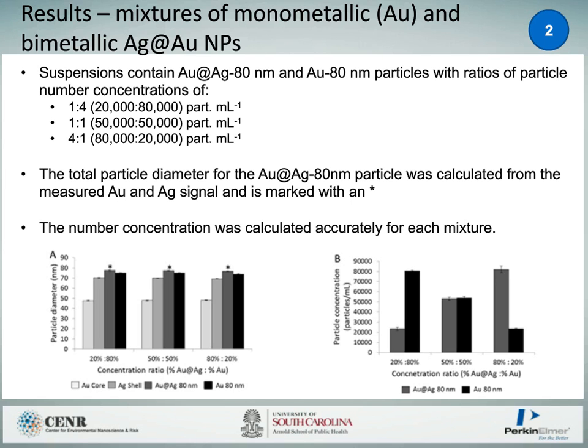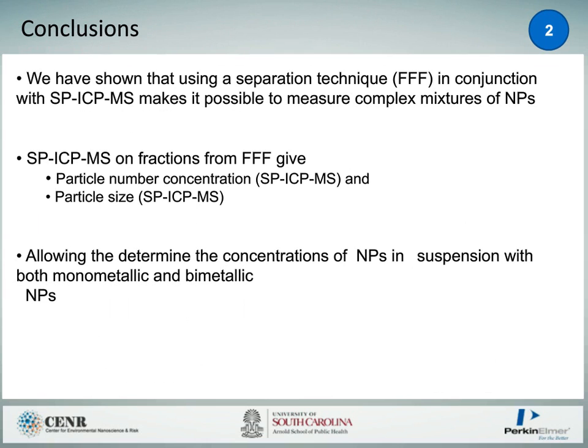So we can actually get the right number of particles and the right size of particles in this case. So I'd like to conclude and say we've shown that using separation techniques like FFF in conjunction with SingleParticle ICP MS, it's possible to measure complex mixtures of nanoparticles. SingleParticle ICP MS on fractions can give you a particle number concentration and a particle size for the particles within that fraction. And we can determine concentrations of nanoparticles in suspension for both the nanomaterials.